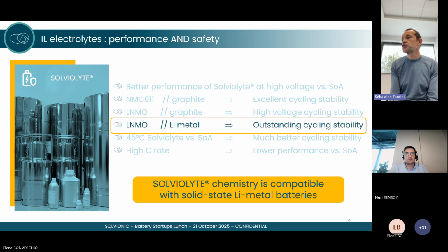We have much better cycling stability, obviously at elevated temperature, since we are using full ionic liquid electrolytes. One of the shortcomings is the low performance at high C rate when room temperature is used. This is due to the slightly higher viscosity of our electrolytes compared to the state of the art.